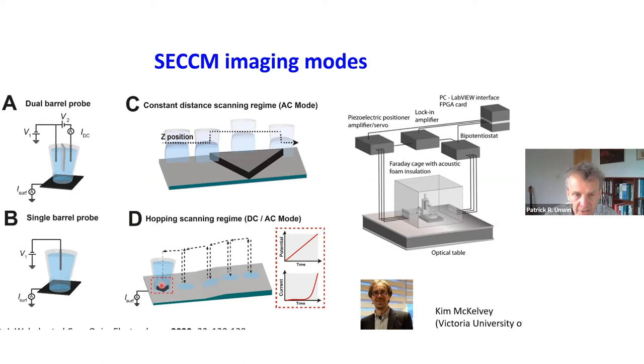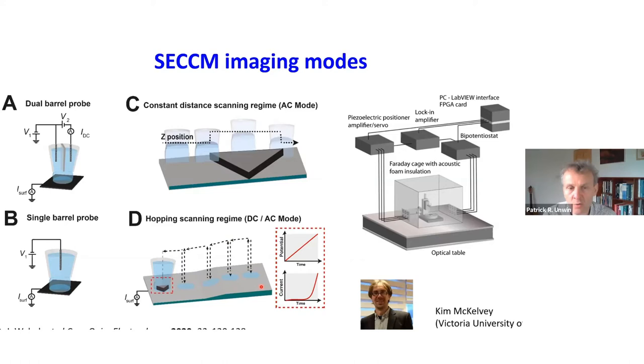With a single probe on a conducting surface, the feedback is that when the meniscus lands on the surface — without the probe itself contacting the surface — we close an electrochemical cell and get a very brief charging current. We can use that as feedback to stop the motion of the probe. This hopping mode is a really nice way to visualize surfaces, and when we land the meniscus we can carry out any conventional electrochemical measurement — linear sweep voltammetry, impedance spectroscopy, or chronopotentiometry.